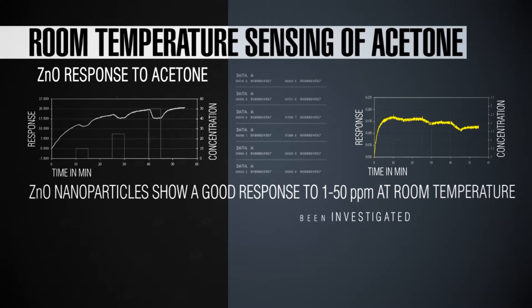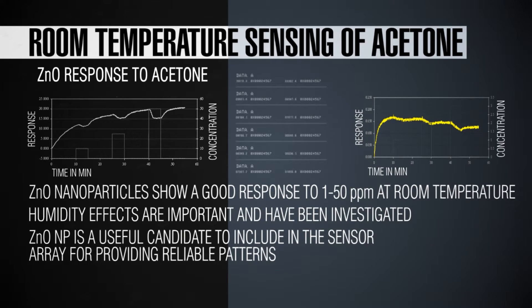I'm showing room temperature sensing of acetone using zinc oxide nanoparticles, which show a very good response from 1 to 50 parts per million at room temperature. Humidity effects are important because when identifying biomarkers in human breath, mind you that human breath is more than 95 percent humidity. Trying to pick out a biomarker signal in a massive amount of water vapor is very critical and challenging.